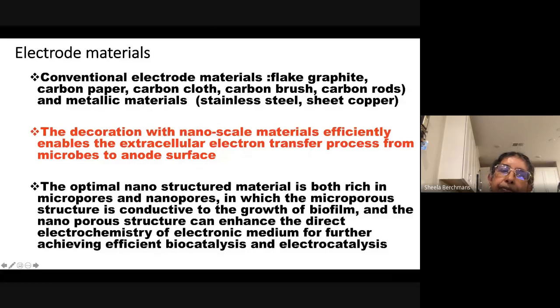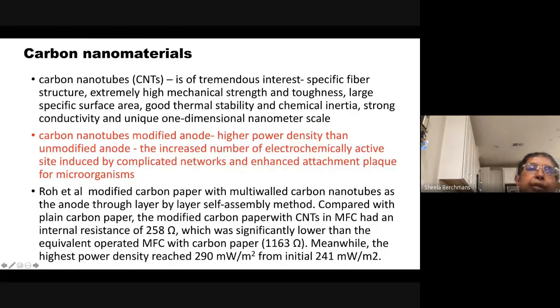Now, the decoration of these electrode materials with nanoscale materials efficiently enables the extracellular electron transfer process from microbes to the anode surface. So when we incorporate nanoscale materials along with these electrode materials, the electron transfer rate increases to a large extent. The optimal nanostructured material is rich in both micropores and nanopores, in which the microporous structure is conducive to the growth of biofilm, and the nanoporous structure can enhance the direct electrochemistry of the electronic medium for further achieving efficient biocatalysis and electrocatalysis. So carbon nanomaterials are mostly being used in microbial fuel cells.